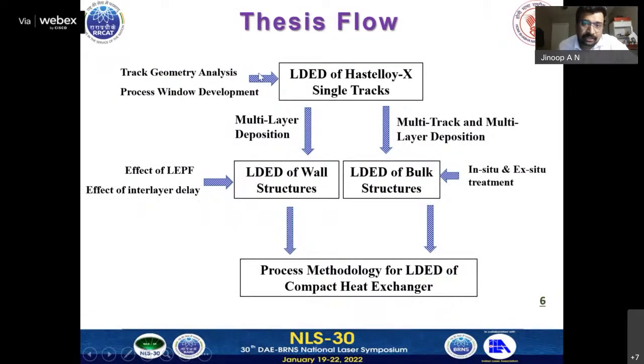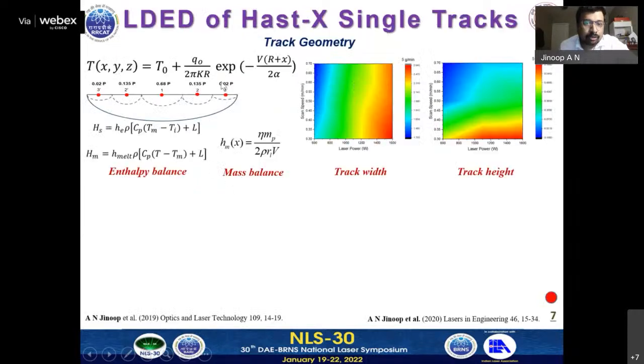So the thesis flow: first we start with single track deposition, where we have two parts basically. One is track geometry analysis, another is process window development. Then we go to multi-track, multi-layer deposition, with wall structures and bulk structures. Finally, we go to the development of the compact heat exchanger. So the first work is on the development of single tracks. First we did the track geometry analysis. We used the point heat source equation and extended it to a Gaussian heat source and tried to predict the track geometry. The track geometry was predicted by using a combination of enthalpy balance approach and mass balance approach.